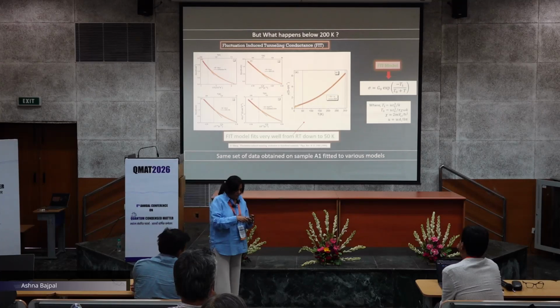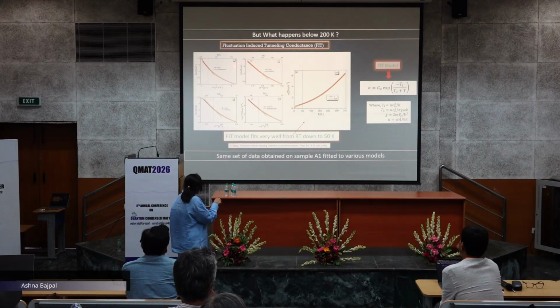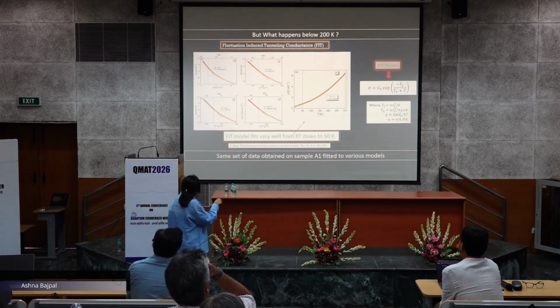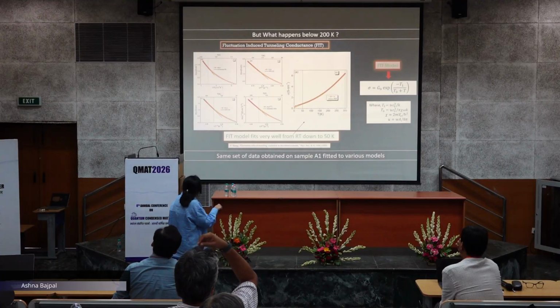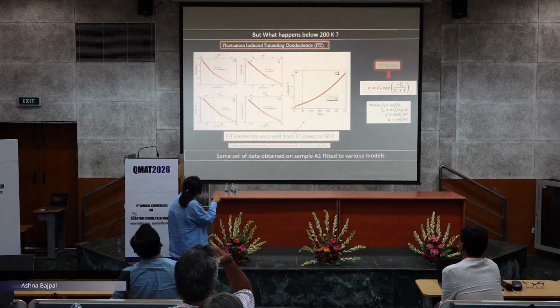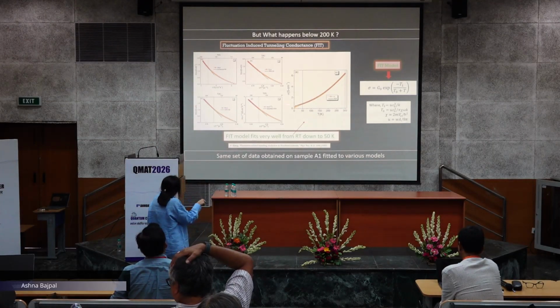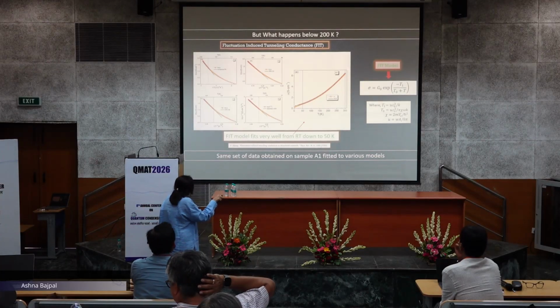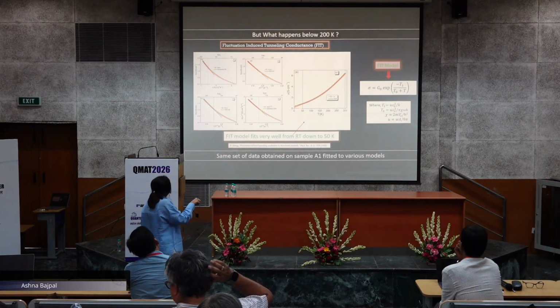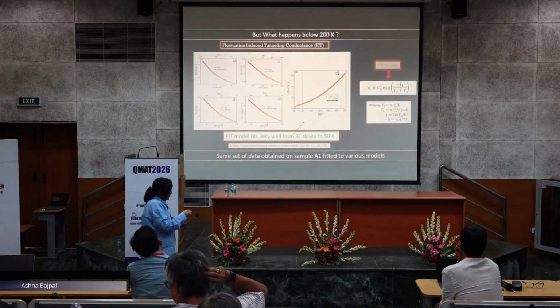So we chose that sample, and that is sample A1, and only in that sample I am showing you the fitting of conductivity as a function of temperature, where all these models fit to a limited range, but FIT fits right from 300 Kelvin to 50 Kelvin. It's a good fit in the same sample.